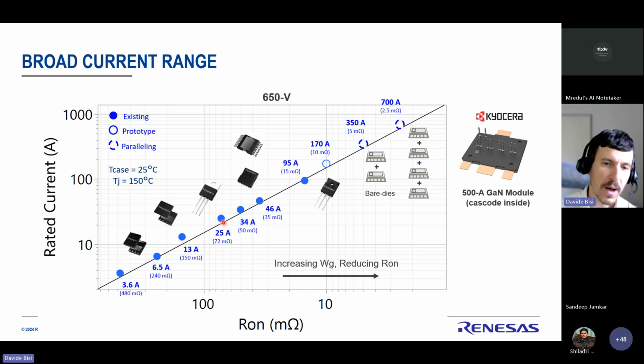Then we have a medium power between 25 amps and 46 amps here, which are used in power supplies for data centers. And our biggest chips for high power are a 15 milliohm product, and we have a 10 milliohm prototype today. The 10 milliohm prototype can carry as high as 170 amps of current. So you can see that it's getting significant. It's getting very seriously high, to the point that it could compete against silicon carbide as well.